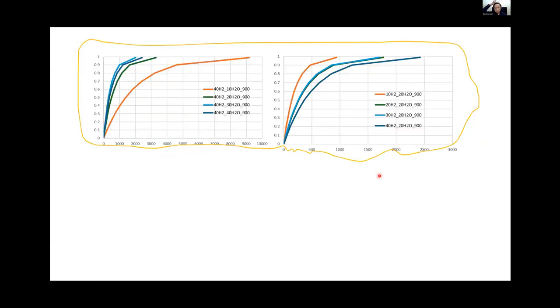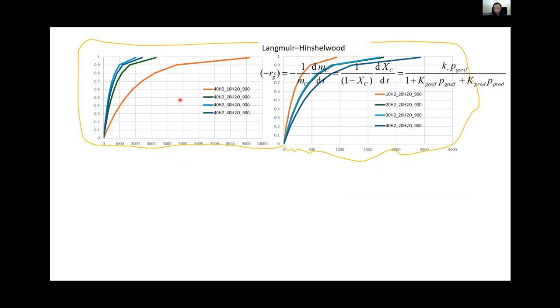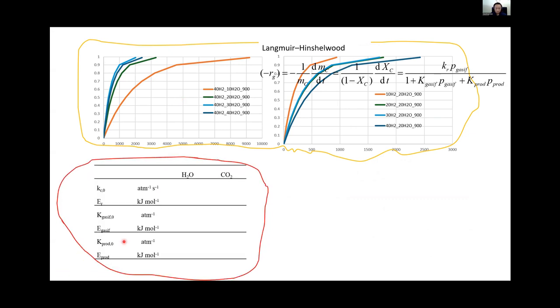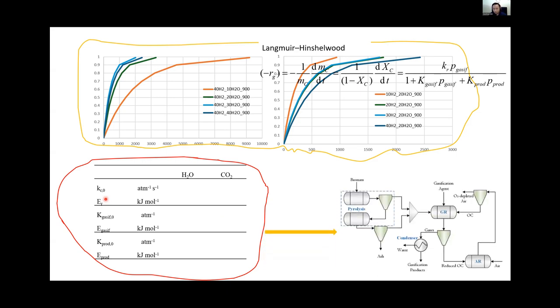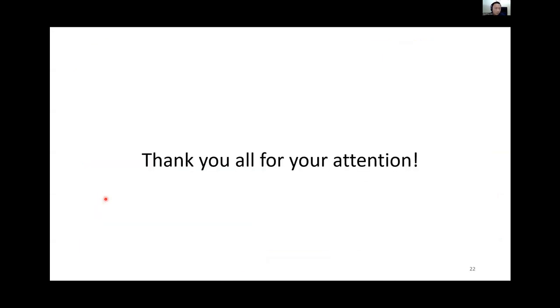These two figures present an example of char conversion data, and the effect of steam concentration and hydrogen concentration can be clearly seen. And with this TGA data, we can get the Langmuir-Hinshelwood kinetics parameters, like apparent activation energy and exponential factors. And we want to use these kinetics parameters to get an accurate process simulation model for the project. Okay, that's all from my part, and thank you very much for your attention.